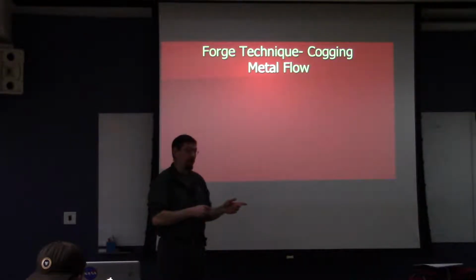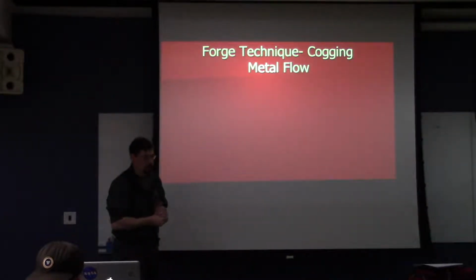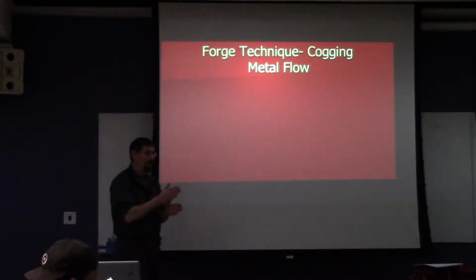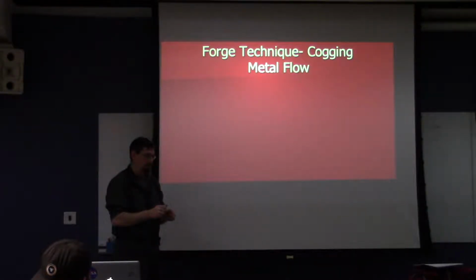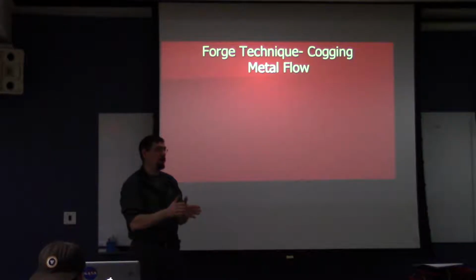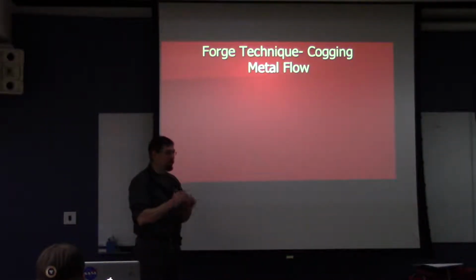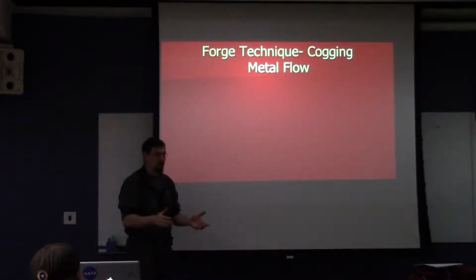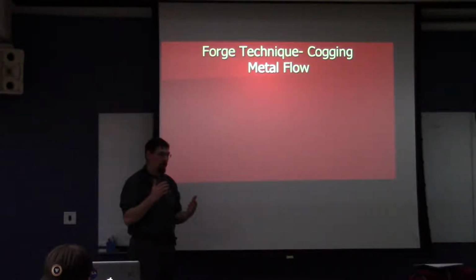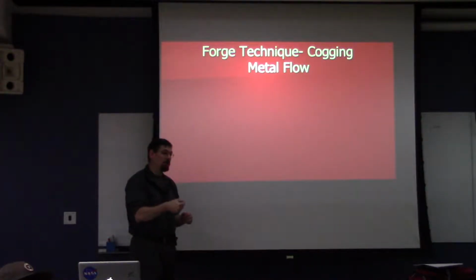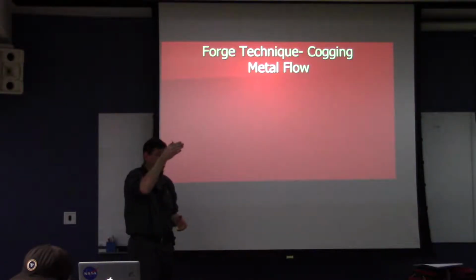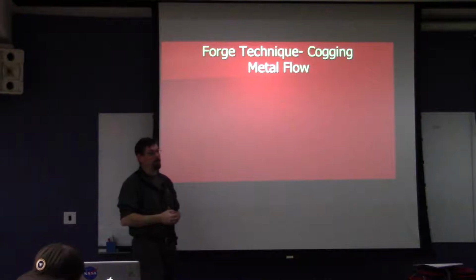Right, you have to balance that with the risk of lapping. As long as you're not going to lap it, which is usually pretty evident when you're in the midst of forging, it's very evident if you're at risk for having that happen. That's really the press operator's responsibility to avoid. It's not hard to see that could happen, and so he can adjust his technique in an instant, because the way our presses are set up, the operator has control over every push of the press. It's a little bit like a video game. It's not exactly like a video game, but he has a joystick that he moves forward and the press comes down, and he pulls it back and the press comes back up. And so for every time that he wants to come down, he can do that, so he can see in real time, I'm getting to a point where it's too deep, I'm going to pull back, so that doesn't happen.